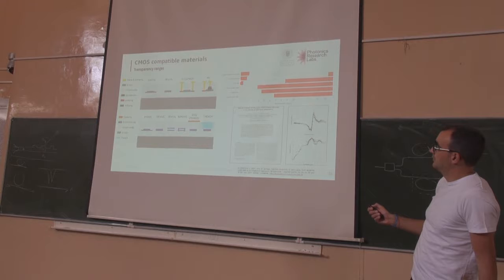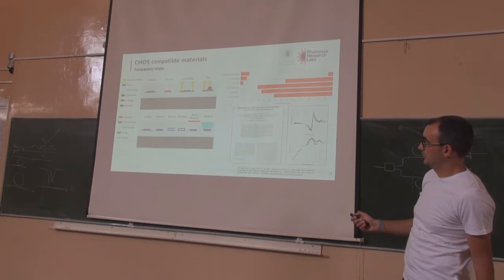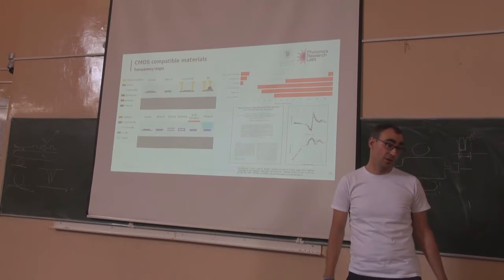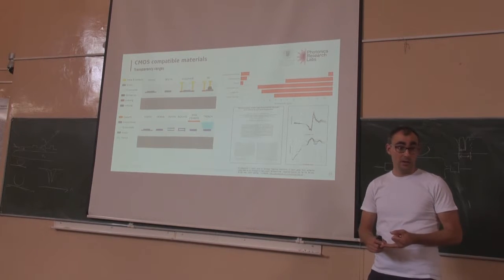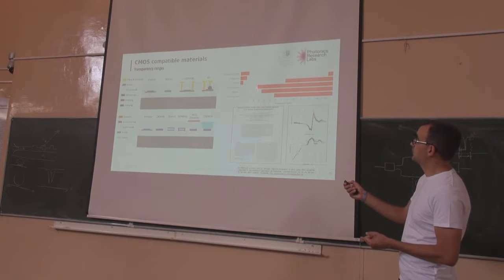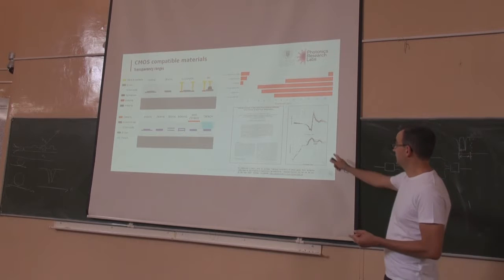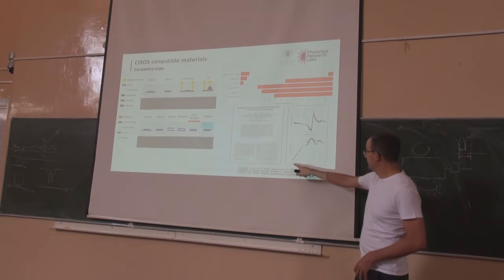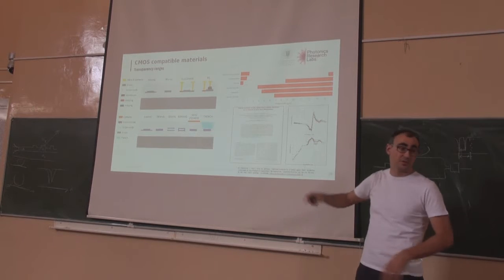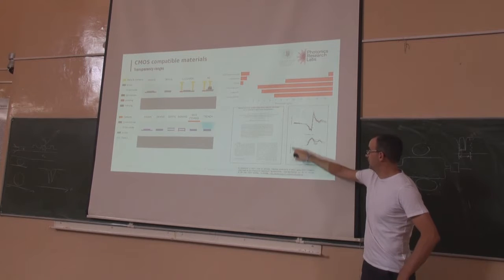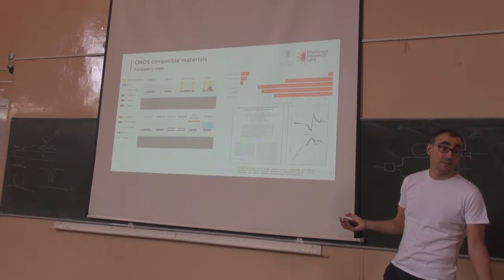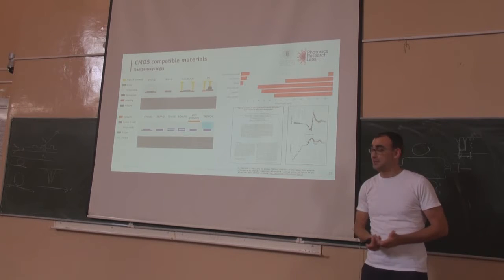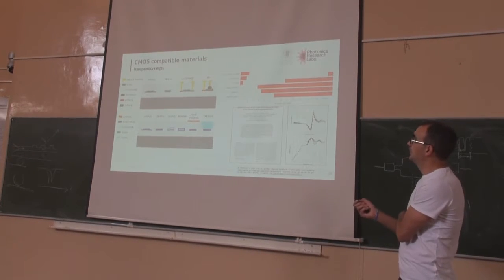But then you have an issue here. Typically, silicon and silicon nitride are surrounded by silicon dioxide in most of the photonic integration platforms that we're using nowadays for biophotonics and for telecom. But the silicon dioxide starts to absorb strongly close to 4 microns. Okay, and you can see here, this is the paper, and the reference is here. This is 2, this is 3.7, and then at 4 the absorption is already very strong. Okay, so this is absorption, nothing and a lot. So you need to build a platform without silicon oxide. That's the message. Even though silicon oxide is a very convenient material and it is very well controlled, you need to build a platform without the silicon oxide. You could also use sapphire, and you could also use silicon nitride.